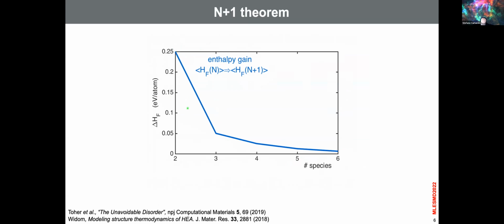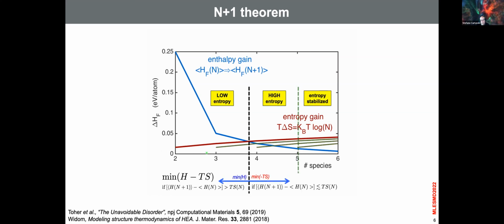So how deep the convex hull grows with respect to the increase in number of species actually decreases with the number of species. All right, so look at here. If you add disorder, which means that you add x log x, like completely random solutions, or you think that here there is one sublattice that is ordered, or two sublattices disordered, or three sublattices disordered, etc. Then you see that there are three regions of the space with respect to the number of species.